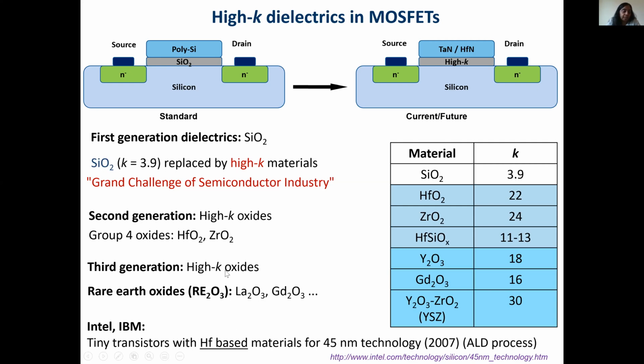Now the current trend is to look for materials which have higher dielectric constants. It's not just the value of the dielectric constant, but they have to be compatible with silicon, with the gate, with the source, because there are new materials also being investigated as a top metal contact. For example, here you have polysilicon. This has been replaced by tantalum nitride or hafnium nitride. And this is where the challenge is, that it should be compatible. The material properties should also be relevant. And of course, the device should function much more effectively.